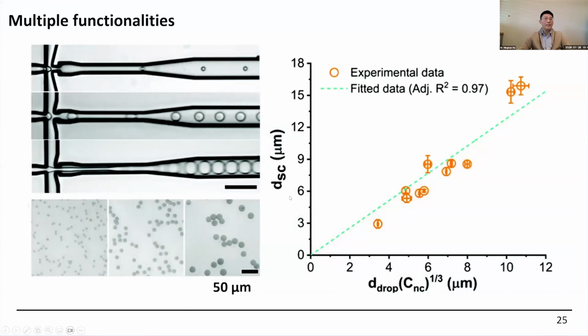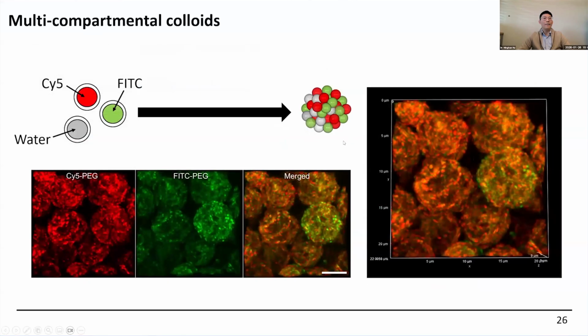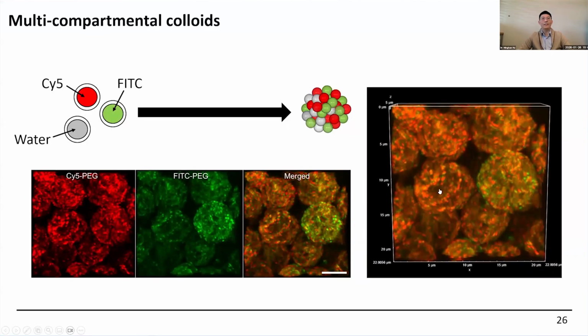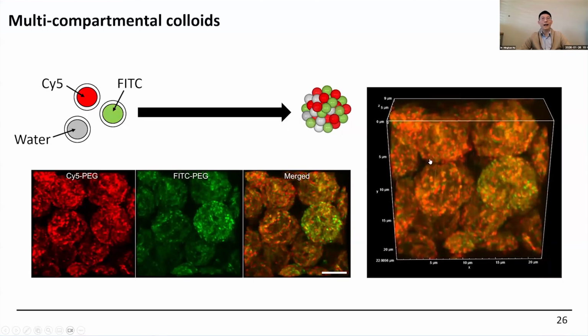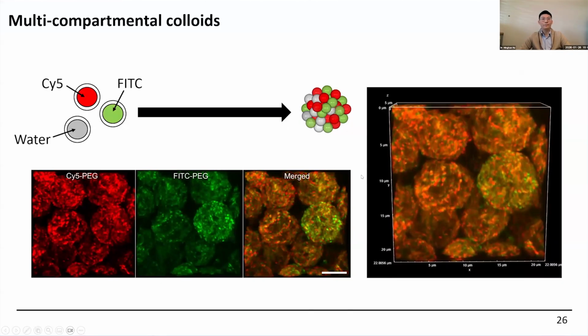And the nice thing is, because we use microfluidics, we can nicely control the droplet size and also the concentration of our nanocapsules within the droplets. And we can further control the final supercapsule diameter from 3 micrometers until around 18 micrometers. And we also encapsulate two different fluorescent dyes, one green, one red. And then we can nicely see they are still maintained inside their building blocks.